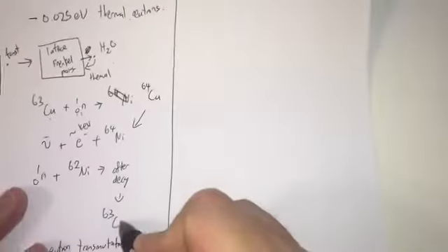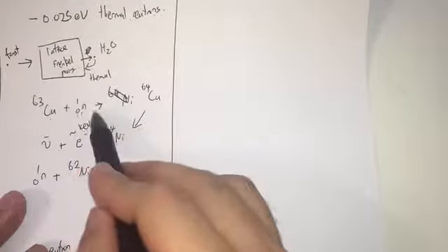When these betas come out, they can come out at several keV to MeV, and this can also cause another collision cascade, or cause ionization, cause the lattice to heat up, etc. And so nickel can be transmuted to copper, nickel 62 to copper 63, and copper 63 can absorb a neutron to become nickel 64. These are just some of the typical reactions that can happen.